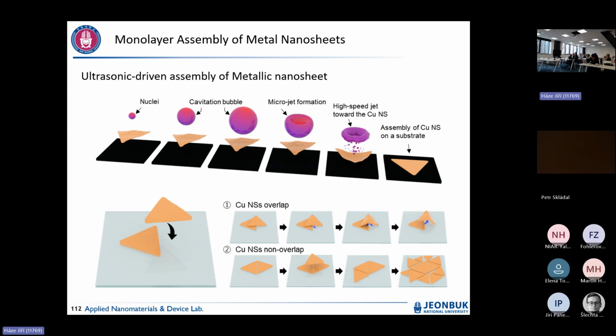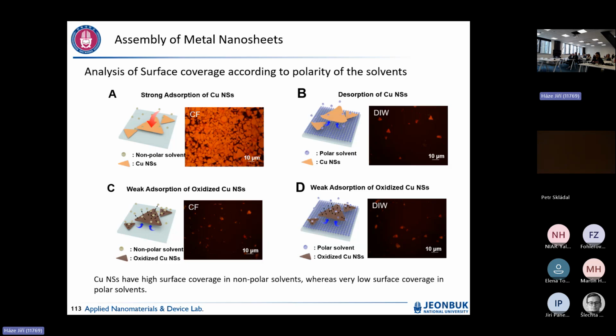But it depends on the relationship between the surface and the solvent you use. When the copper sheets overlap, there should be some gap, right? The bubble is generated there, then it lifts off. When you process this again and again, the nanosheet looks for its proper position. Then we tested the relationship between the solvent and the surface property of the substrate, and found it happens with a hydrophilic surface with a non-polar solvent.